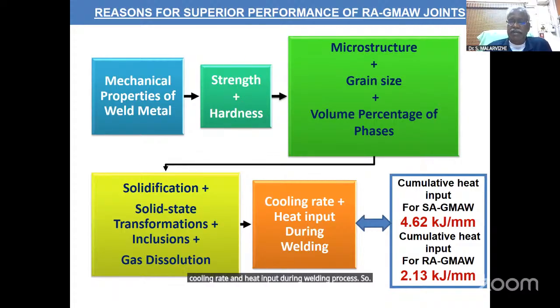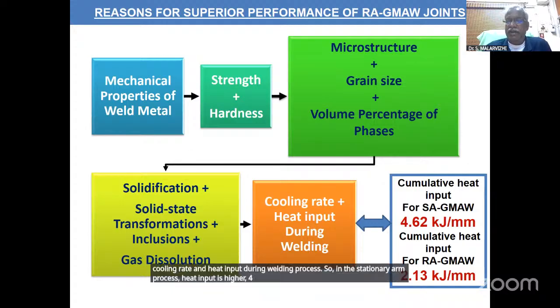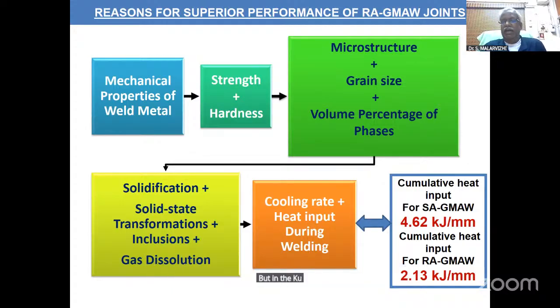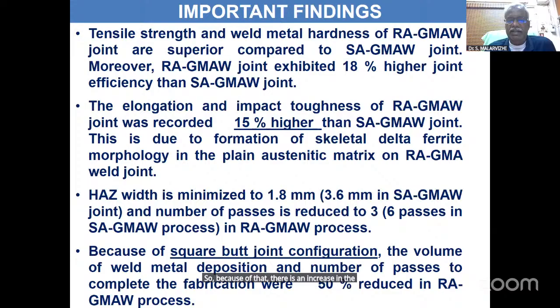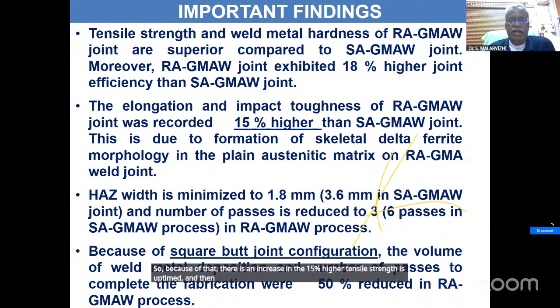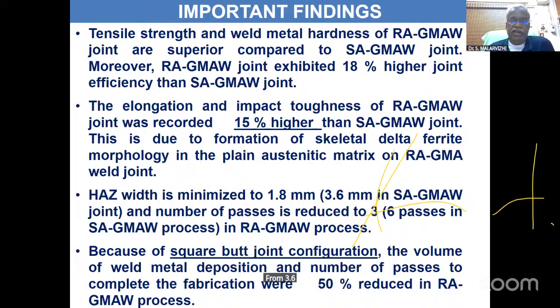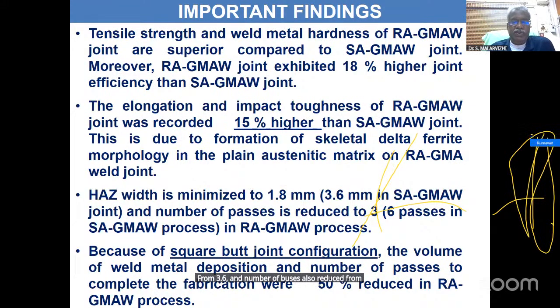So in the stationary arc process, heat input is higher, 4.62 kilojoules per mm. But in the rotating arc, the cumulative heat input is only 2.13 kilojoules per mm. That is the reason the cooling is faster, and that changes the morphology of the delta ferrite from globular into the vermicular microstructure. Because of that, a 15% higher tensile strength is obtained, the heat affected zone width is minimized to 1.8 millimeter from 3.6, and the number of passes is also reduced from 6 passes to 3 passes.